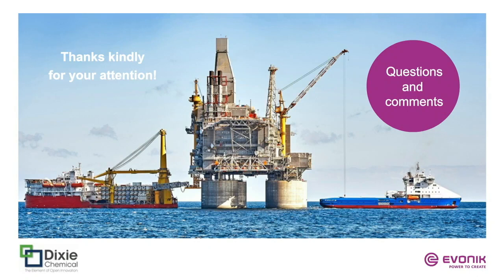Take a shot at it, and then Jeff, feel free to comment if you want to add something to my answer. So just like any monoanhydride epoxy reaction, you would use the same kinds of catalysts and accelerators as with the BTDA systems. The common examples are tertiary amines like either BDMA or DMP-30 or imidazoles. And then you can also use latent accelerators instead of actives based on your process. Current work that we're doing is actually using liquid accelerators for ease of incorporation in the system, and we will be also looking at additional accelerators even if they are not liquid.